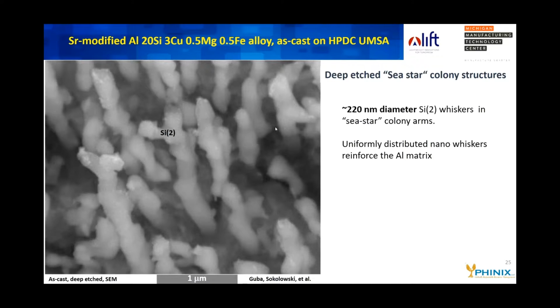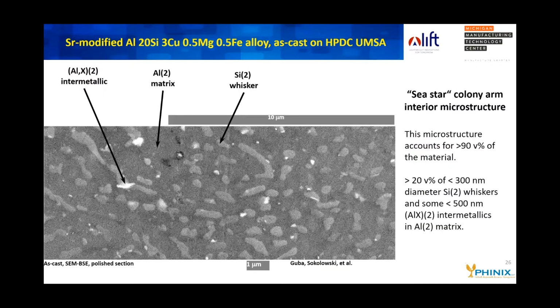And this is a picture of the whiskers and the micron marker is at the bottom. And you can see that they're about 220 nanometers average diameter and quite long, and also very uniformly distributed inside of that sea star colony structure.